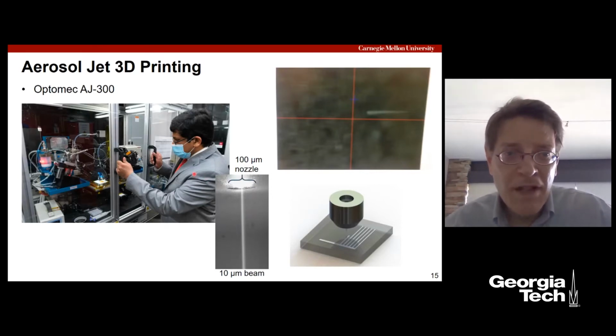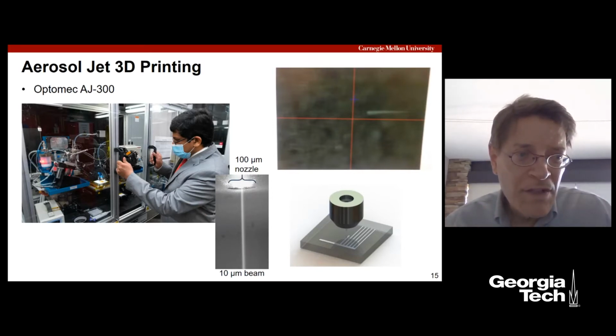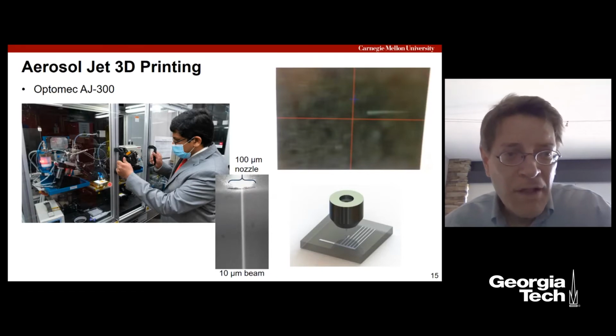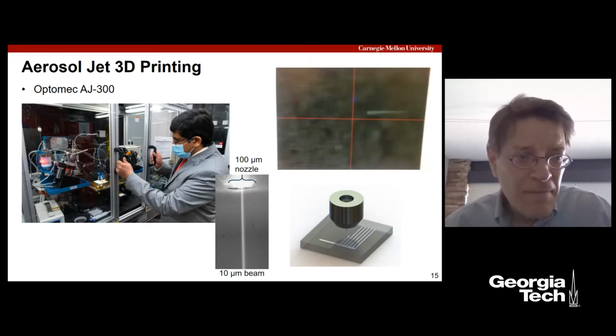You see Professor Panat here with his mask on, opening the machine we have at CMU. The aerosol system is over on the left, and you can see something on the platen that they're printing. I think this is probably printing on polyimide right now under the jet. Typical nozzle sizes are anywhere from 300 microns down to 100 micron, and it shoots this aerosol. In this case, the smallest beam size would be on the order of 10 micron. I got a short video, if I can work it, that just shows